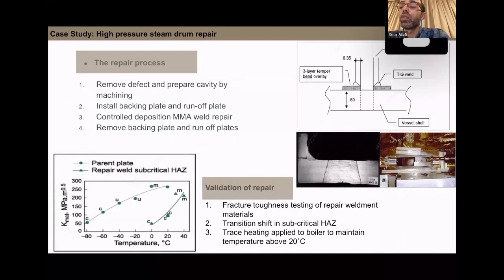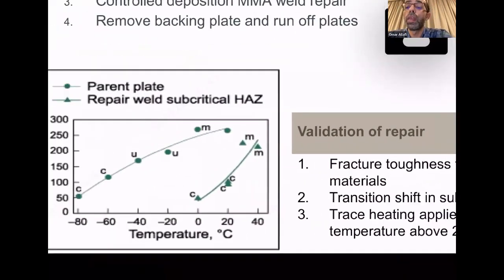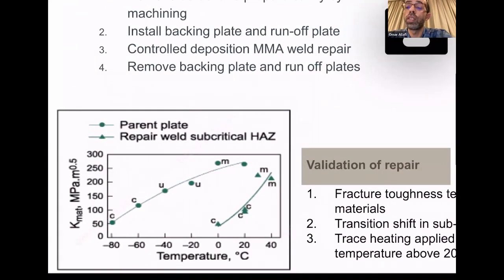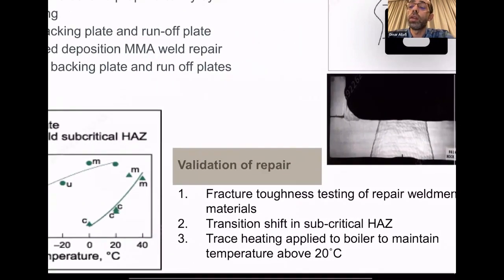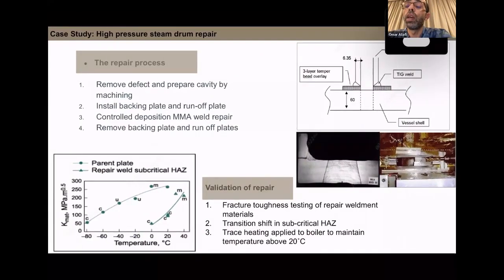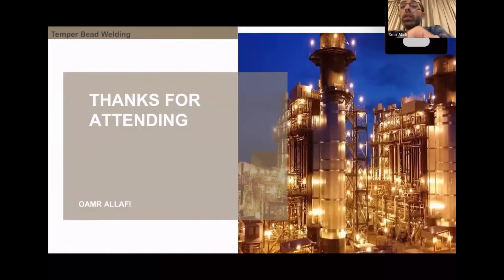In fracture toughness, the fracture toughness was slightly changed. As we can see here, the toughness of the weld has changed. It has lower toughness at lower temperature. So what they did is provide steam tracing to the weld joint to protect against brittle fracture. And this is one of the cases where temper bead was successful as an alternative to PWHT.